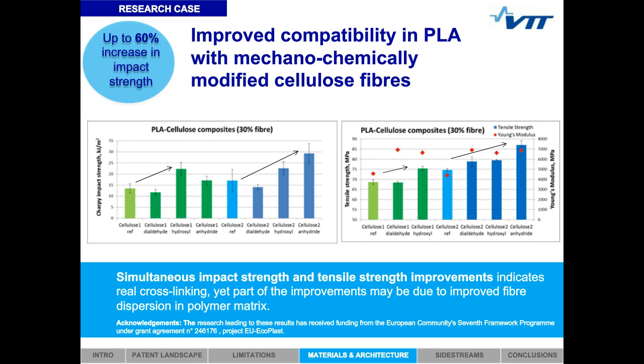In the second example, we again utilize this VTT compactor and the mechanochemical modification method to improve the performance of our natural fiber reinforced PLA composites. In this case, we tried a different type of chemical additives with two different kinds of cellulose fibers. And as you can see in the graphs shown on the slides, we were able to significantly improve the performance of the cellulose fiber reinforced PLA composite. In the best case, we were able to improve the impact strength of PLA by 60%, which is quite a significant improvement considering that the major weakness of PLA material is typically the low impact strength.